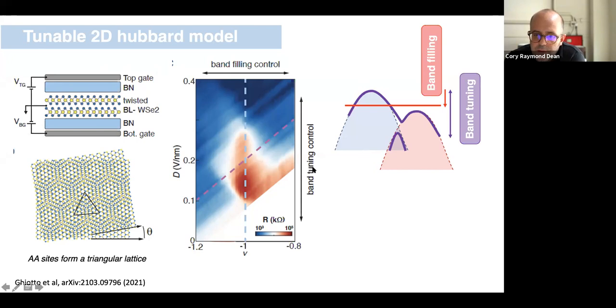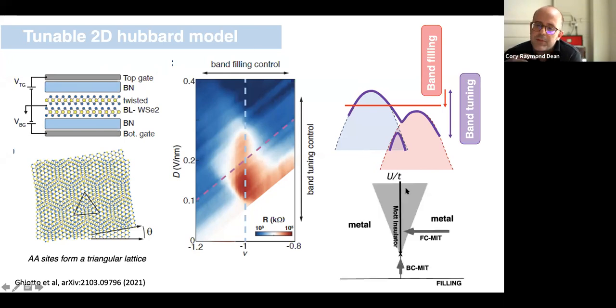So here I'm just showing cutting through this diagram in one or two ways. Because generically, one expects that the Hubbard model has this kind of cartoon phase space that you can access, where at exactly half filling, you have a Mott gap that emerges. And what's interesting is that you imagine that you can tune through this Mott gap either by varying the filling, so either doping into and out of the Mott gap or doping into and out of exactly half filling, or through some modification of the bandwidth itself. Or another way to say that is through some modification of the strength of how strongly correlated the system is.